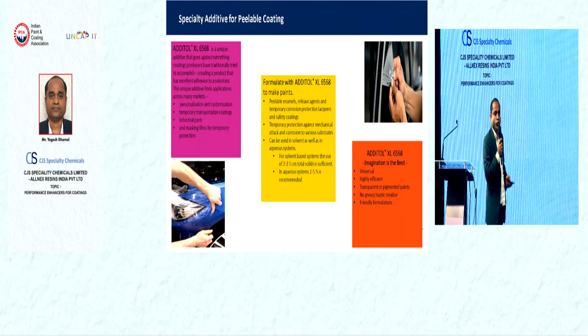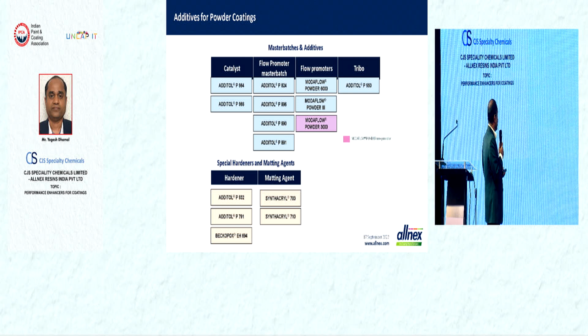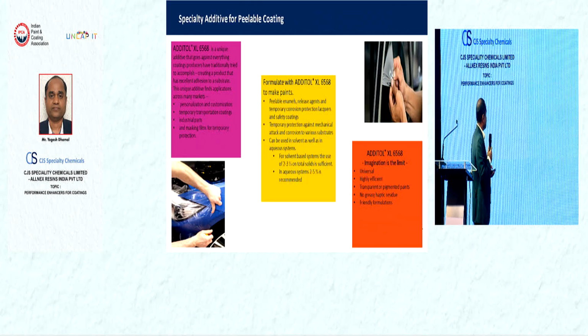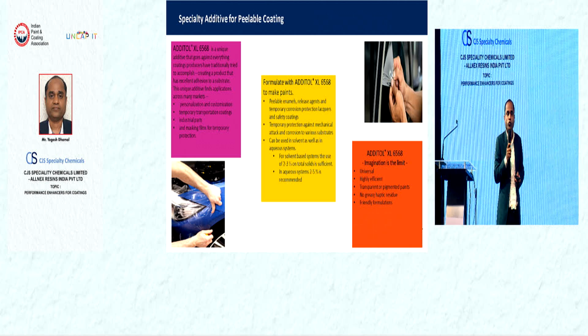Then a very unique product we have is a specialty additive for peelable coatings. So basically this ADDITOL XL6568 is an additive that goes against everything coating producers have traditionally tried. Generally, our paint producers ask about adhesion promoters to improve the adhesion performance of the coating. But here we have an additive which is an anti-adhesion promoter.